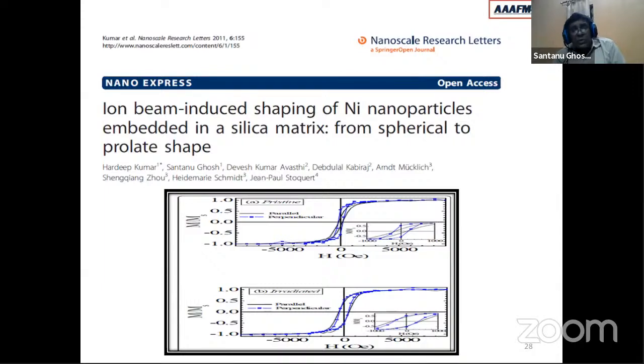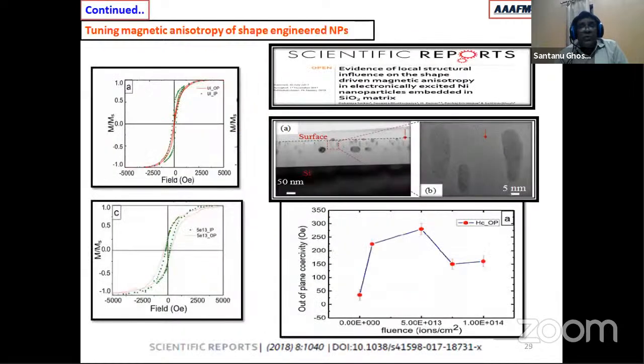Now we have used shape engineered particles, and shape engineered particles show a magnetic anisotropy. If we look very carefully, if we change the incident fluence, what we observe is that the out of plane coercivity, which is also an indication of the magnetic anisotropy, peaks at a particular fluence of 5 × 10^13 ions per centimeter square. It happens because the particles get elongated maximum at 5 × 10^13 ions per centimeter square, because after that the particles actually get dissolved in the system because of very high incident fluence. So one can tune the magnetic anisotropy by this process.